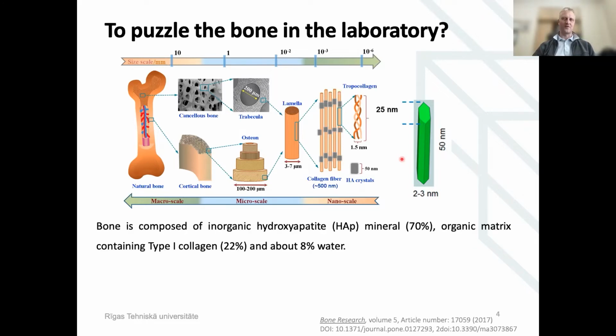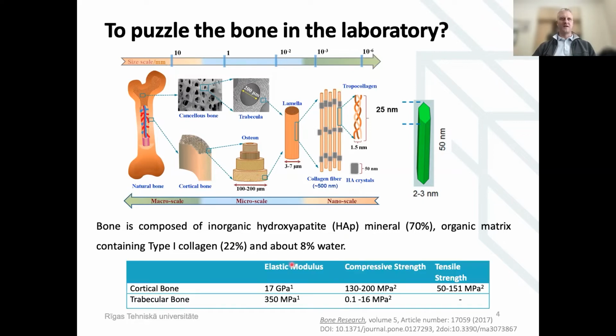And now let's look at the composition from a material point of view. So we forget all the cells, we forget the blood vessels, we forget the nerves. So what we have is a composite of the inorganic phase, which is built up from the hydroxyapatite. And what is very important, the amount of the hydroxyapatite is really high. It's about 70%. And then we also have the organic matrix, and that's the collagen, about 22%, and only about 8% of water. So this combination is the one that explains why we have these kinds of mechanical